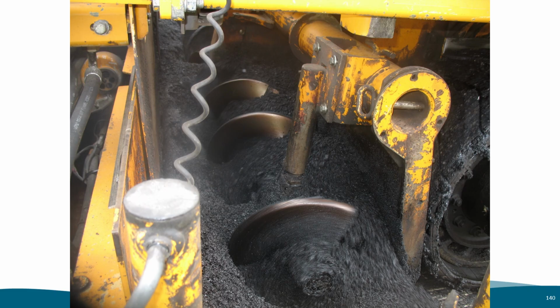This is a picture of the augers that are located at the back of the paver, just before the screed on the left. Contractors can and will add additional augers and extensions when the lane width increases, according to the plans. The thing to remember here is that the contractor understands and is proficient at placing the auger extensions to minimize the stopping and starting process of the paver. A lack of material run through the auger process can leave a bump or dip in finished asphalt surface.